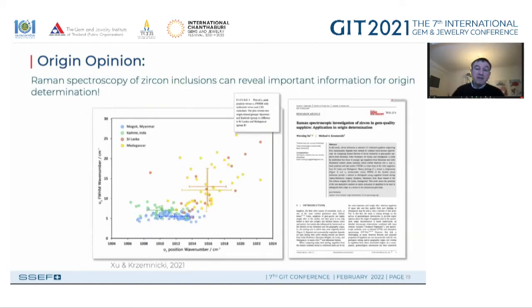And here is a plot when we take in more origins. This is a publication which we have done together with Venture and from the Gübelin lab, showing the Raman peak position versus the full width half maximum of the main zircon Raman peak for different origins. And you can see that, let's say, Mogok, Myanmar, and Kashmir zircon inclusions all show very narrow shape. So they are blue and green, and then you have Sri Lanka and Madagascar with much larger full width half maximum.